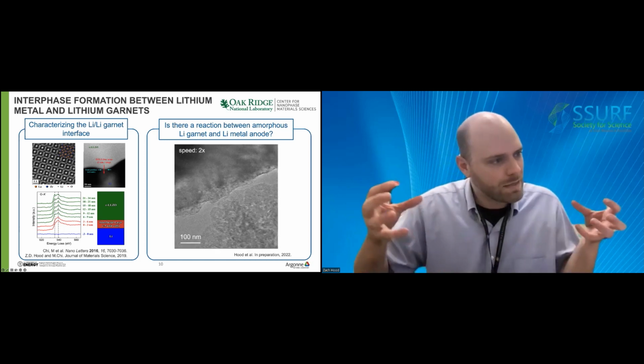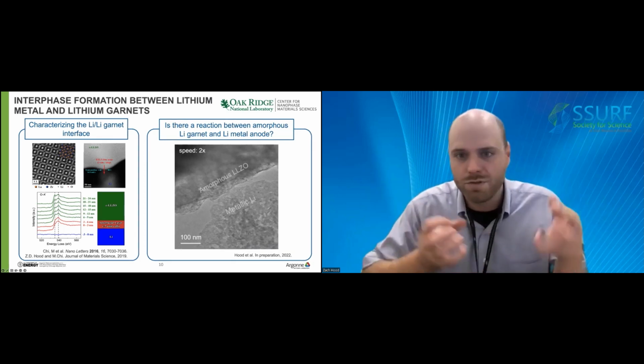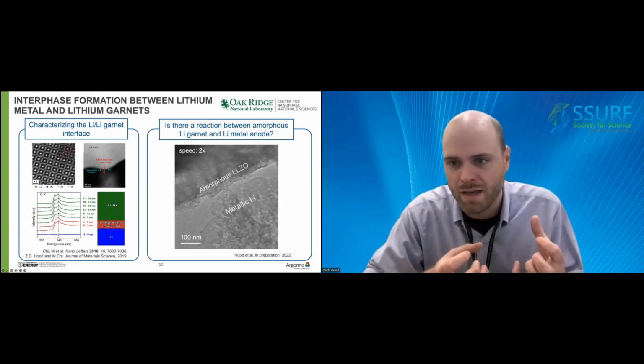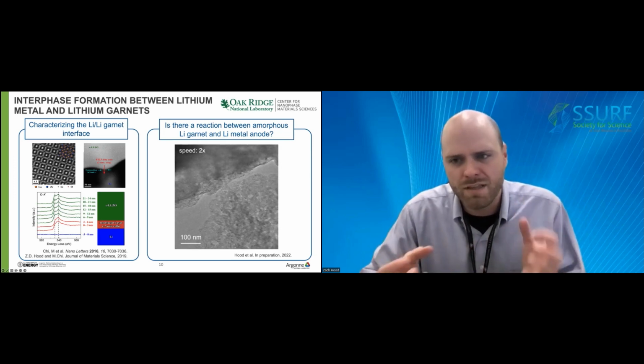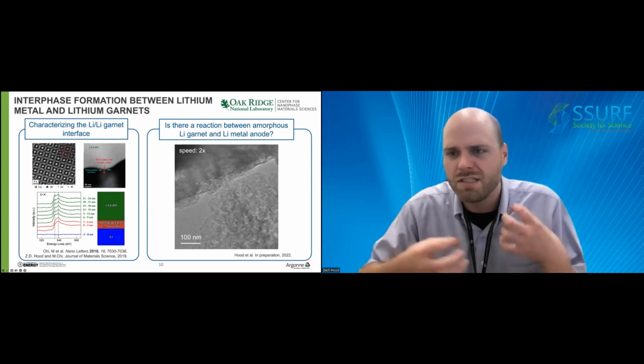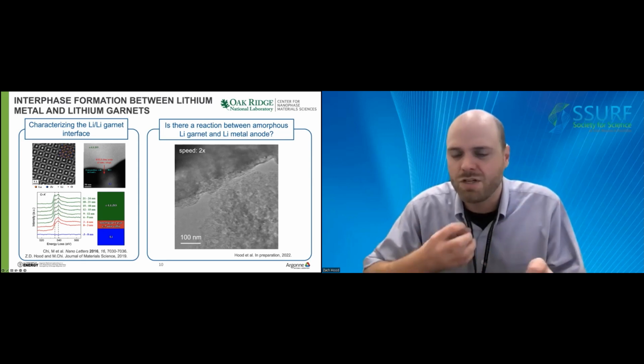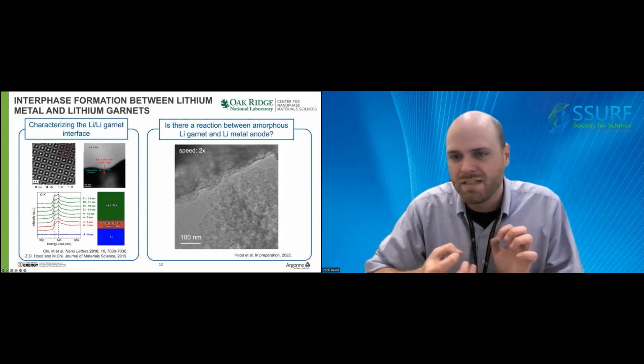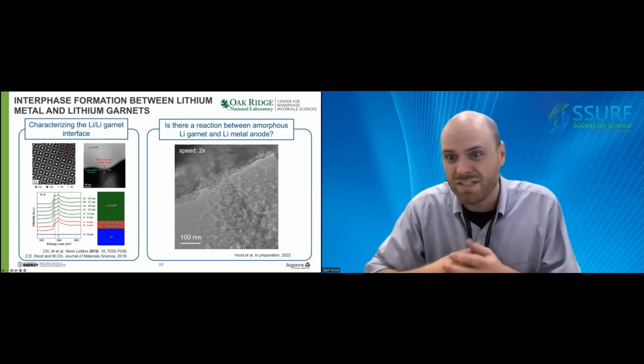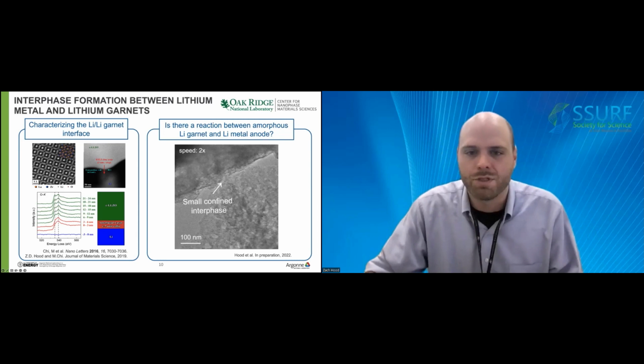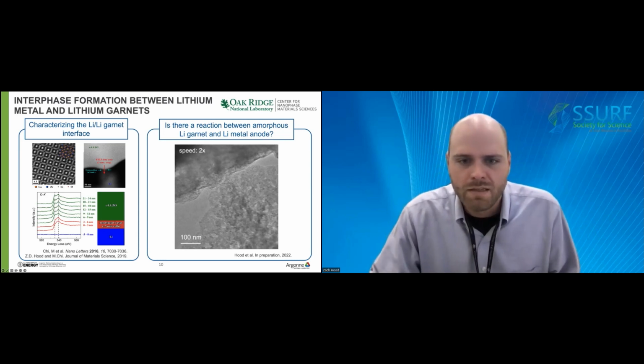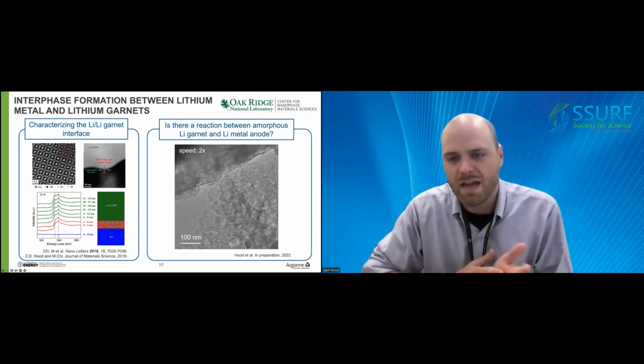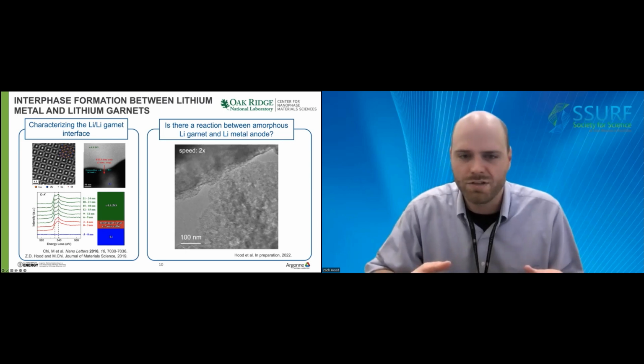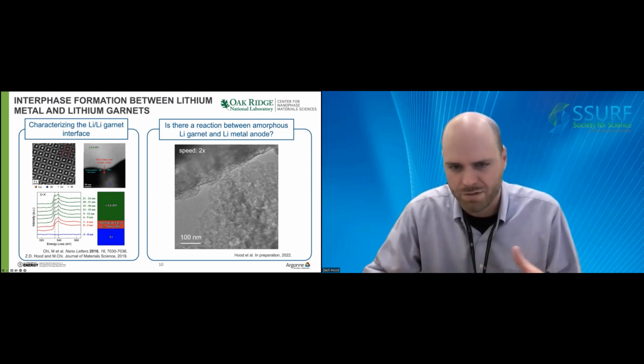So, as we touch the metallic lithium to that amorphous lithium garnet, in comparison to the lithium phosphorus oxynitride materials, we do not see or observe a significant change of that interface. In fact, if there is any change at this interface, it is significantly smaller than what we observed with LiPON. The EELS data on the lower left-hand side of this slide schematically shows what happens on the electronic structure.